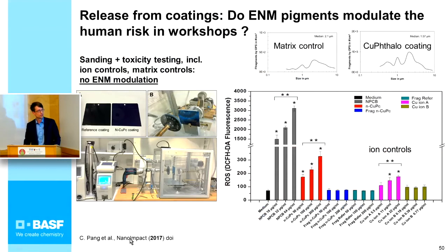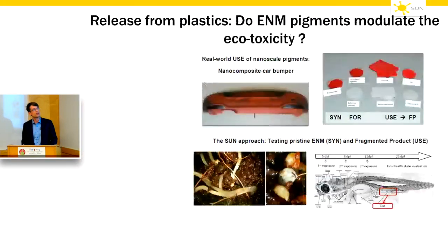And this was work from Shengfang Pang, a postdoc, published in Nano Impact, just accepted. And that's just one study that adds to many previous studies from the Nano House project, again from the NRCWE, that looked at different polymers with titania, silica, or CNT fillers, including in vivo studies, and they confirmed the same conclusion that the toxicity is only weakly, if at all, modulated by the presence of the nanomaterials in these fragments. Now, I went one step further.